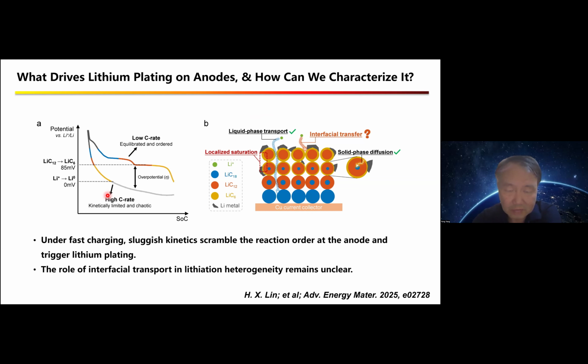We think about that normally, lithium plating happens at fast charging. Under fast charging, sluggish kinetics cause scrambled reactions at the anode, and then trigger lithium plating. So lithium plating is apparently a kinetically determined reaction.